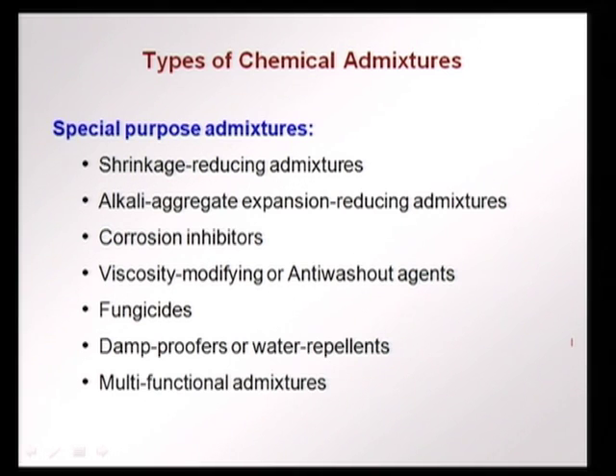Viscosity modifying agents or anti washout agents are used a lot in self compacting concrete, because there we want the concrete to flow without segregation, we need a concrete that is very sticky. It is also used a lot in underwater concreting, where concrete is poured underwater and we do not want the concrete to be washed away. Other special purpose admixtures not used very often are fungicides, water repellents mixed into the concrete. Multifunctional admixtures are where you have admixtures that have more than one purpose. They act maybe as a shrinkage reducing admixture and also a superplasticizer and so on.